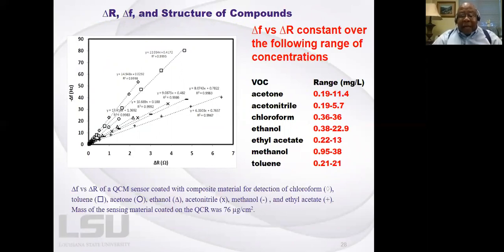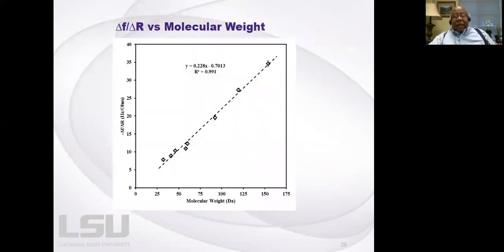And again, why is that? I said, well, try one thing. Plot delta F over delta R versus molecular weight, just out of curiosity. For some reason, I had a gut feeling that maybe this has something to do with molecular weight. Just do that plot. And when he did that plot, he got a linear relationship with an R squared of 0.99, which is an incredible correlation. So delta F over delta R was related to molecular weight.